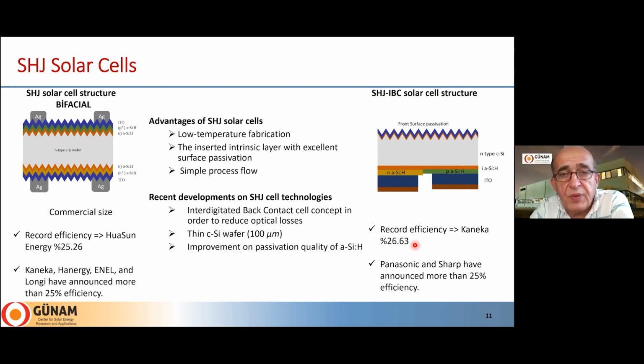So the record efficiency was obtained by the Japanese company Kaneka. It was 26.6. This is the record efficiency for the whole crystalline silicon industry, not only heterojunction. And Panasonic and Sharp have announced more than 25% efficiencies with this device architecture.